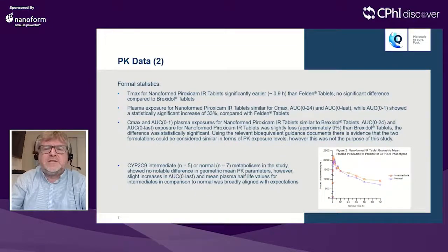Formal statistical analysis of the PK data from the study found significant differences in that the nanoformed piroxicam immediate release tablet Tmax was almost an hour earlier than that for Felden, and plasma exposure over the first hour post-dose for the nanoformed piroxicam immediate release tablets was increased by 33% in comparison to Felden reference. When comparing the nanoformed piroxicam immediate release tablets to Brexidol, the maximum and early exposure levels were similar, whilst later exposures were slightly reduced, although there's evidence that they could be generally considered similar in terms of PK based on relevant bioequivalence guidance documents. This wasn't a formal aspect of this study.